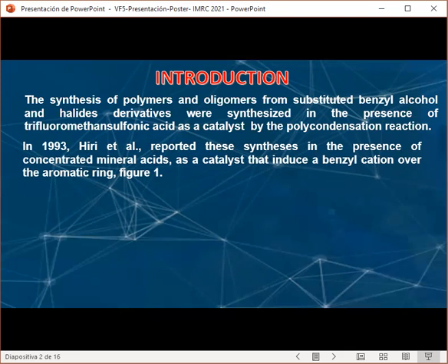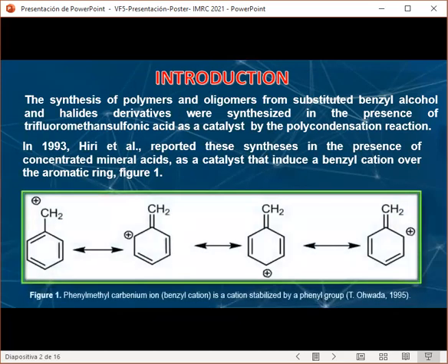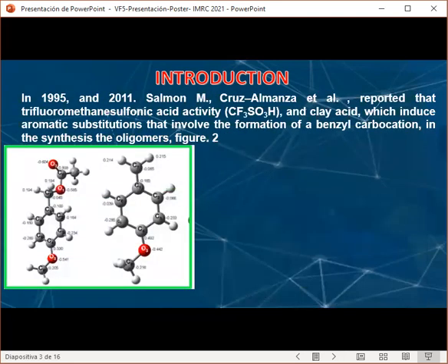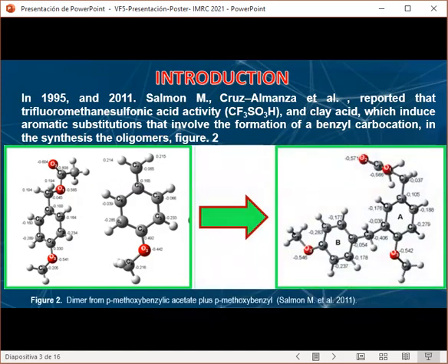In 1993, Hiri et al. reported this synthesis in the presence of concentrated mineral acids as a catalyst that induces a benzyl cation over the aromatic ring. You can see it in Figure 1. It is important to mention that from 1995 to 2011, Salmon, M. Cruz Almanza, among others, have reported that trifluoromethanesulfonic acid and clay acid induce the aromatic substitution that involves the formation of the benzyl carbocation in the synthesis of oligomers from benzyl alcohol and derivatives. You can see in this slide the formation of the dimer from the paramethoxybenzyl acetate plus paramethoxybenzyl.